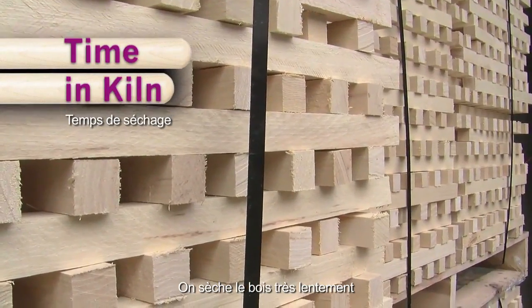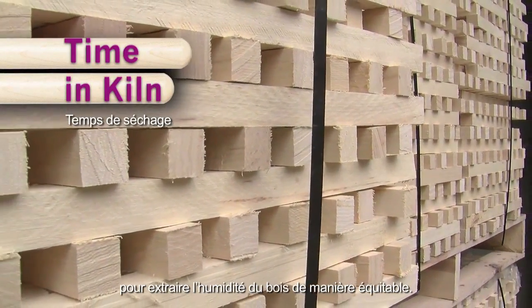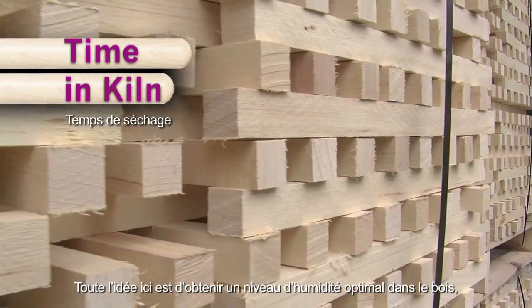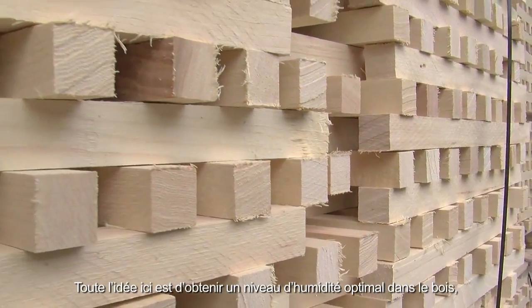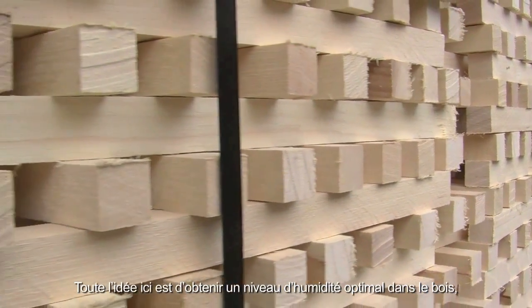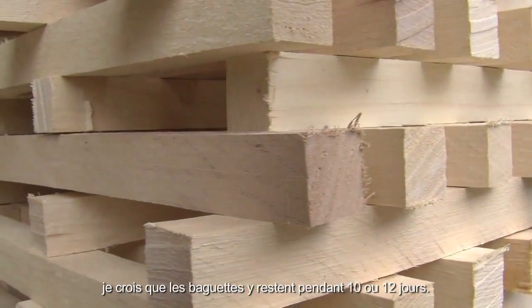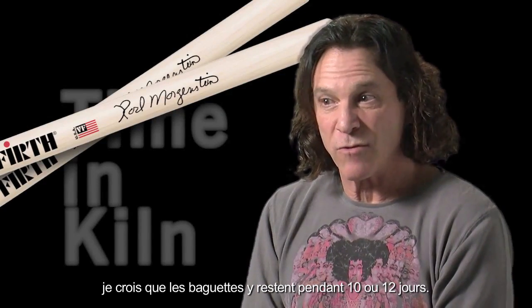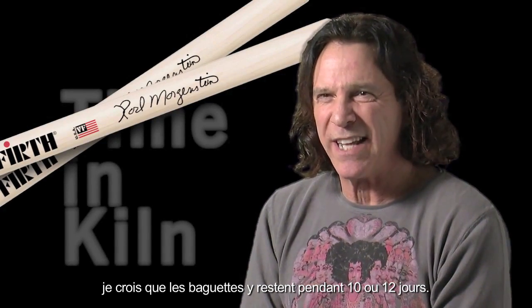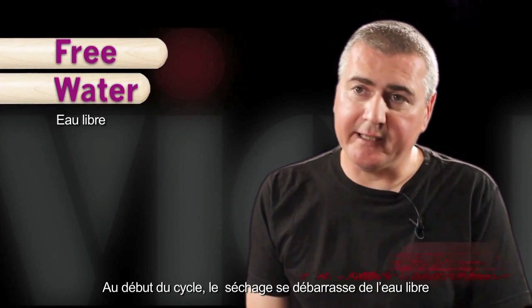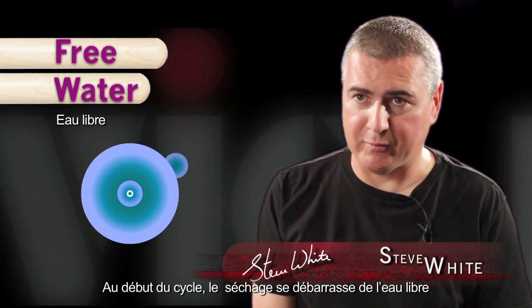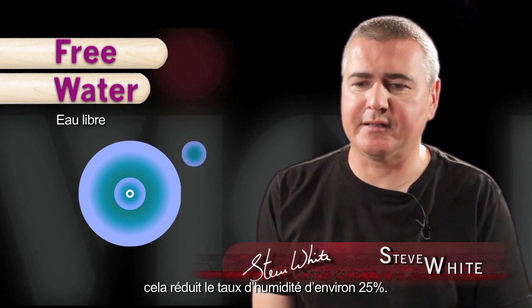We dry the wood very slowly to extract the moisture evenly from the wood. And the whole idea is to just get the level of moisture in the wood down to that optimum level. I believe sticks are in there somewhere between 10 and 12 days. The beginning of the kiln cycle gets rid of the free water. This actually reduces the moisture content by about 25%.